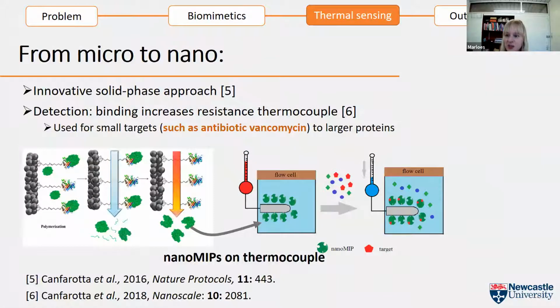Now, the way this works from a more fundamental perspective is that we have quite an innovative technique for how we produce these polymers, using a solid phase approach. If you want to know more about it, you can have a look at the papers here. We first attach whatever we want to measure to a glass bead. We polymerize around it, and then we can use the solid support as an affinity medium. We use a certain elution based on temperature or other things, and then we only collect the particles that have a very high affinity for what we want to detect.